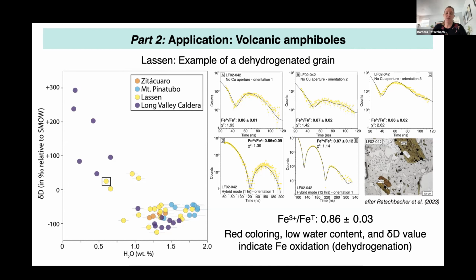And we came up with a ferric over total iron ratio, which is rather high, 0.86, but it really fits our assumption that this is a grain which has experienced dehydrogenation and post-crystallization oxidation. And it also fits well with the observation we can see in the microscope, which is that a lot of grains in the sample actually show this red coloring, which is indicative of iron oxidation.